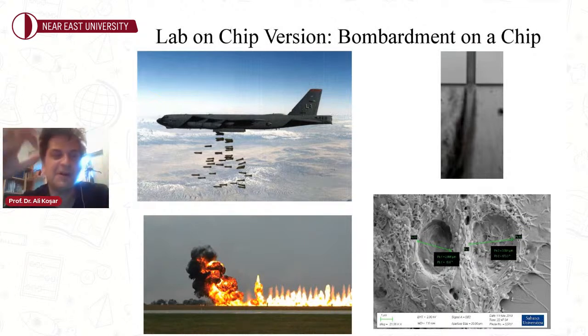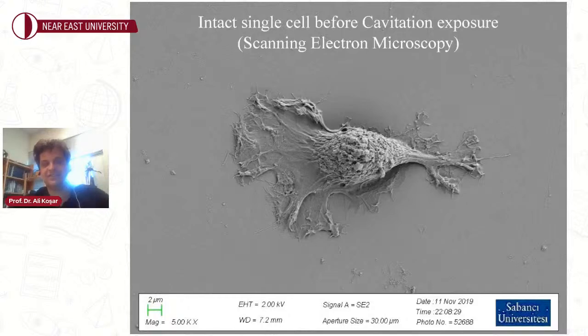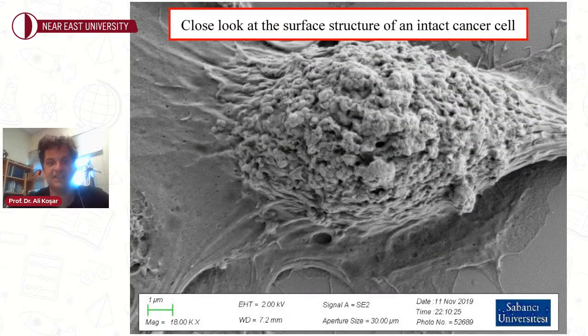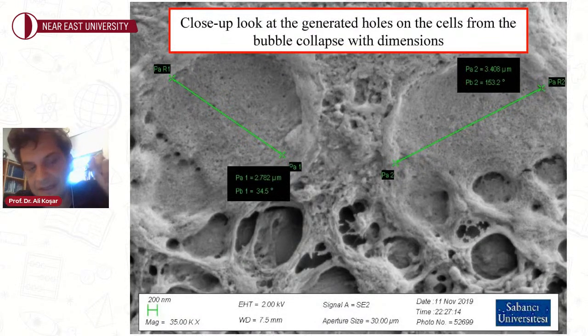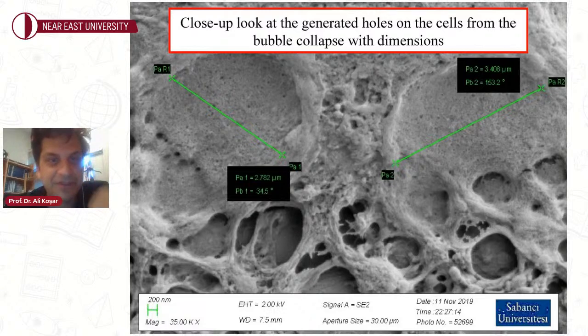So we have carpet bombardment from a plane like this, but we could also use this approach for this micro scale version of this. So we can bombard a cell so that with the bubbles we can have craters on the cell, as you can see. And the size of the crater we have is close to the bubble size. So we have a breast cancer cell here, right? You can see. And upon exposure for maybe a few seconds, we have craters which were caused by the bubbles. So here, for example, the diameter is about maybe 3 micrometers.